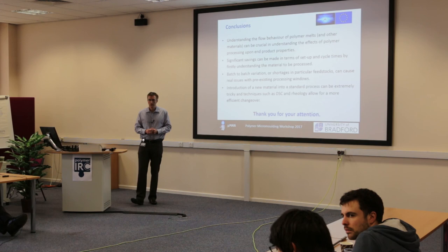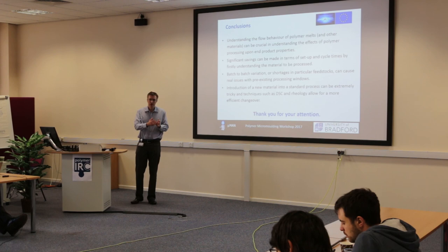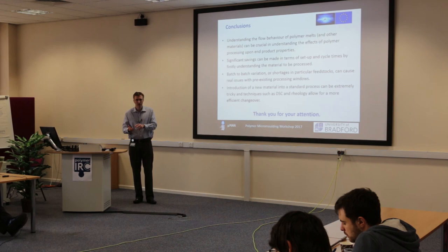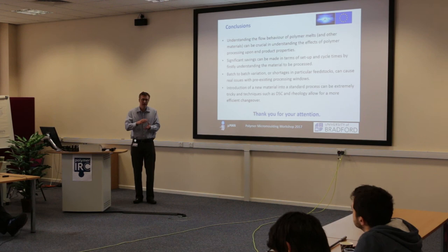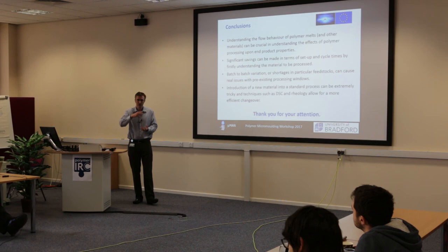It's a little bit more complex than that because lots of polymers are semi-crystalline, so they have partly crystalline regions and partly amorphous regions. Amorphous polymers don't technically have a melting region, they just become softer and softer and have more and more energy, so the molecules flow. But crystalline materials need to get enough energy to break the crystalline phase for the crystals to melt.